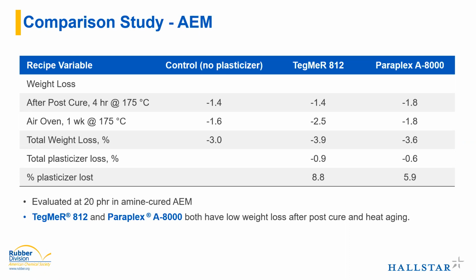That was the high polarity, high molecular weight, but still monomeric material, versus a typical, fairly standard, relatively low molecular weight polymeric material. Both of them showed some additional weight loss, as would be expected by adding them, in both the post-cure and after a week at 175 C, but not a significant amount. We saw slightly more with the monomeric versus the polymeric, as would be expected, but again, not significantly more.